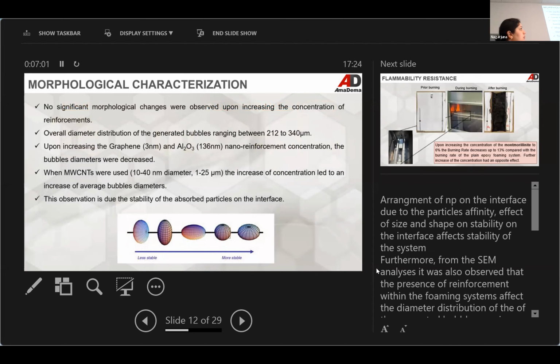Now, just a quick summary of what we have observed. We haven't observed any significant morphological changes, meaning that we started off with open cell foams, and what we got was open cell foams. The overall diameter distribution ranges between 212 to 340 micrometers. In the case of graphene and aluminum oxides, we have observed that the bubble diameters decrease. In contrast, when we incorporated multi-wall CNTs, we've seen that the average bubble diameter actually increases. We're postulating that this effect is due to the shape and size of the incorporated nanoparticles and their stability on the interface.